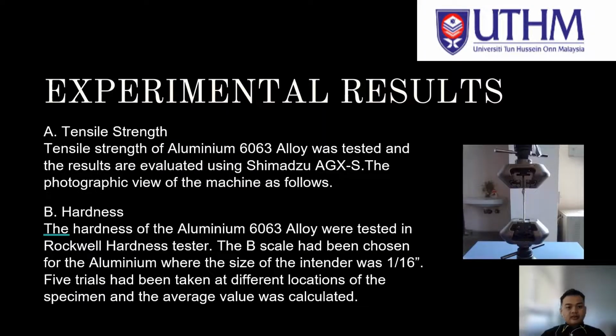Next is for experimental results. A. The tensile strength of aluminium 6063 was tested and the results are evaluated using Shimadzu AGX-S. The photographic view of the machine is as follows. And then B. For the result for hardness, the hardness of the aluminium 6063 alloy was tested in a Rockwell hardness tester. The B scale had been chosen for the aluminium, where the size of the indent was 1/16. 5 trials had been taken at different locations of the specimen and the average value was calculated.